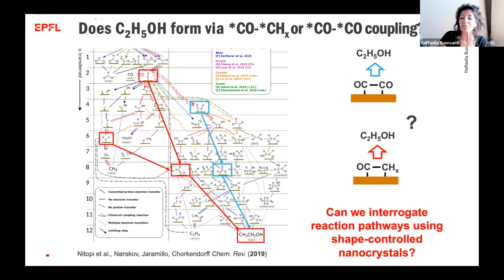And we do find that the selectivity of our particles is also preserved at this high current density. And now, more recently, we have also started to utilize these shaped nanocrystals to interrogate, in a quite unique way, the reaction pathway, which I mentioned earlier is quite complex. So in particular, for example, if we want to form ethanol, because now we can form methane and ethylene, what about alcohols, which are also desirable products to obtain? In terms of theory, there have been two pathways reported for alcohols.